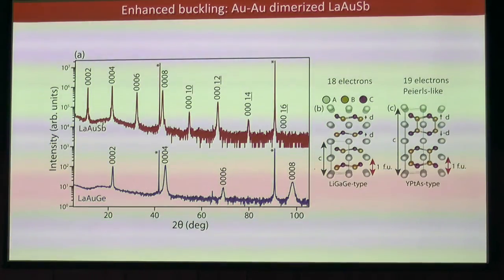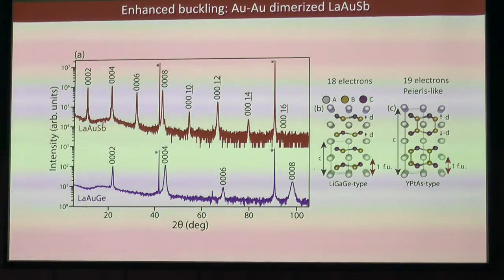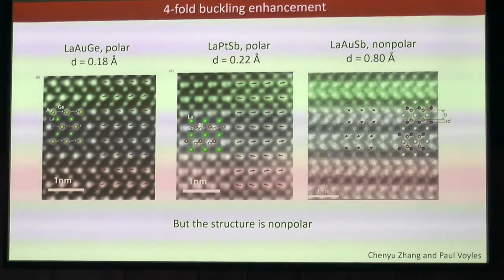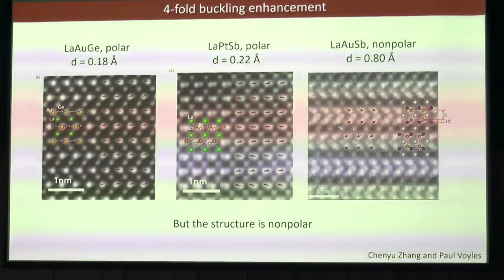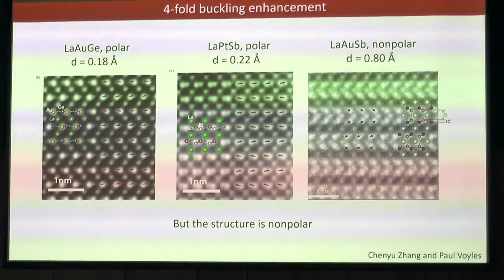Okay, so we've grown similarly structured compounds. If you take lanthanum gold germanium and replace germanium with antimony, it has one more valence electron. So this now is our 19 valence electron system. We now see half-order reflections in the X-ray diffraction. This corresponds to a doubling of the unit cell along the c-axis. And from cross-sectional TEM, we can show that yes, we actually do enhance this buckling magnitude by about a factor of 4 compared to these 18 electron compounds. But again, the structure is nonpolar.